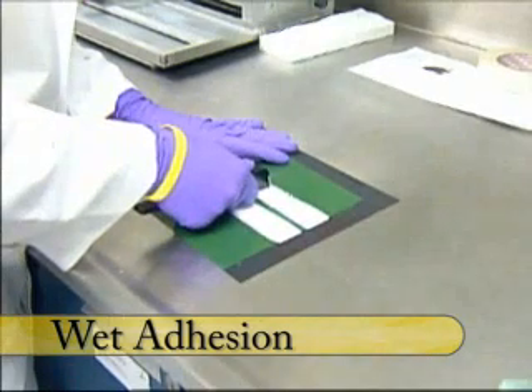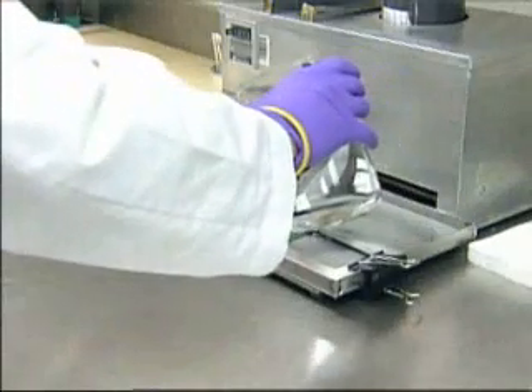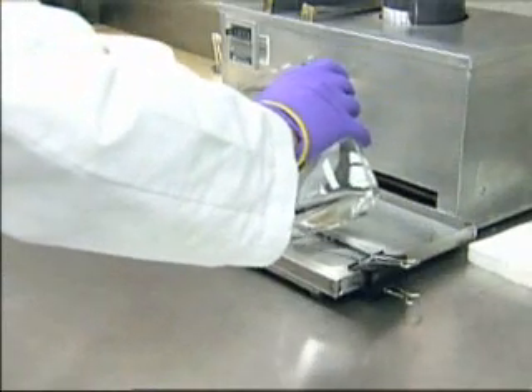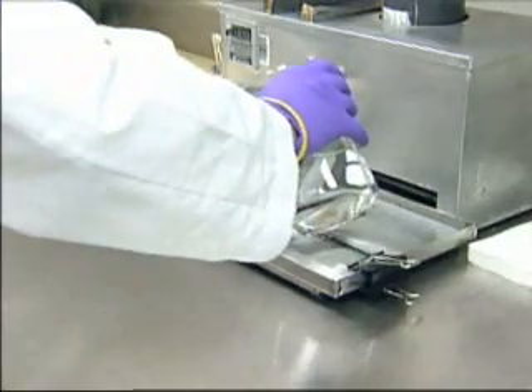After drawdown, cuts are made into the film to form 60 quarter-inch squares in the center of the film. Panels are soaked for up to 30 minutes in ambient tap water and then mounted in a washability tester with 20 milliliters of water. The panel is then scrubbed for up to 500 cycles or until all the squares within each block are completely removed. The test quantifies the loss of adhesion to a substrate after exposure to high humidity, condensation, or precipitation.